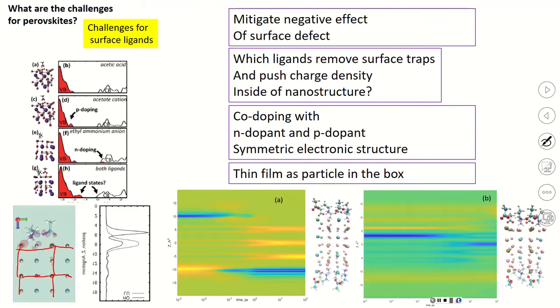So if one repeats these calculations for the lead-rich surface, there is a slight, partial migration of the negative charge to the surface, but on average it is much more homogeneous and it promises to be a better light emitter. So this is the main result of the work. So I'm just wondering, in the first case, is the hole localized in the top half or in the bottom surface? Is that the same thing or does that have any significance? No, because the system is identical in this case. I mean, symmetric in this case.